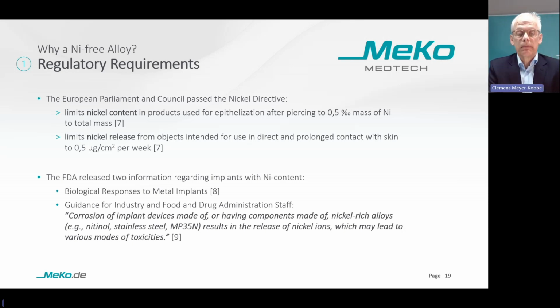The problem of nickel allergy is well recognized by the national authorities. Regulatory requirements and restrictions regarding the nickel content of devices for human bodies are shown in this slide. First, there is the European Parliament and Council, which passed a nickel directive to limit the nickel content in products used for epithelialization to 0.5 per mil mass of nickel to total mass. This is 500 parts per million. This directive also limits the nickel release from objects intended for use in direct and prolonged contact with skin to 0.5 microgram per square centimeter per week.